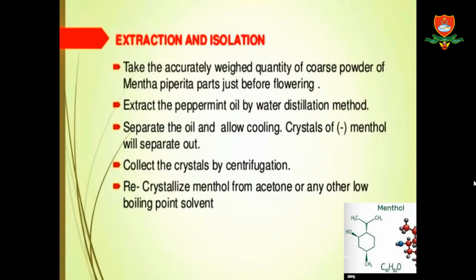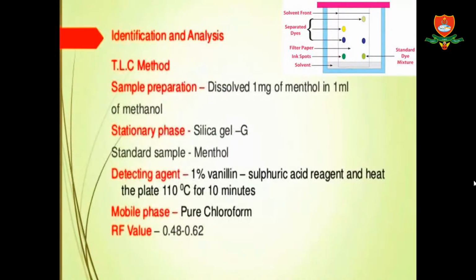So the extraction and isolation. We took an accurately weighed quantity of coarse powder of Mentha piperita parts just before flowering. We extracted the peppermint oil by the water distillation method, separated the oil, and allowed it to cool. The crystals of menthol will be separated out. We collected the crystals by the centrifugation method, and also recrystallized menthol from acetone or any other low boiling point solvent. Next, ma'am.